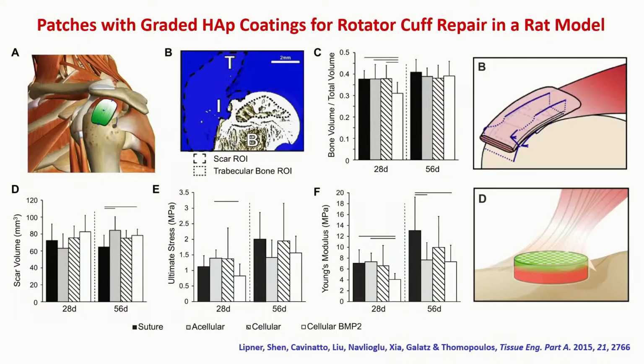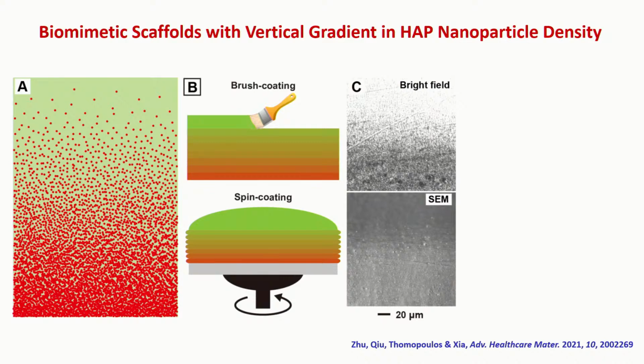Of course, this scaffold, again, has to have a transition in terms of composition and mechanical strength along the vertical direction. Okay, that's basically the original concept. You want to bridge the tendon and the bone with this gradual transition in terms of mechanical properties. And in this case, we rely on the formation of something we call a density gradient of nanoparticles. These nanoparticles are just hydroxyapatite nanoparticles you can commercially get from Aldrich.